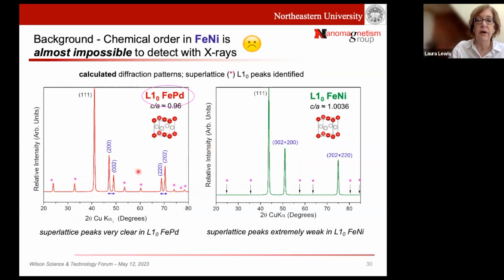If we have something that scatters quite nicely, we can also have iron and palladium put together. If we look at them with X-rays, these are the same crystal structure, different elements. The stars are the signatures of that order. So we're lucky with iron palladium. Yes, we see lots of order when it's ordered, but iron nickel, even if it's perfectly ordered, we just can't see these peaks.